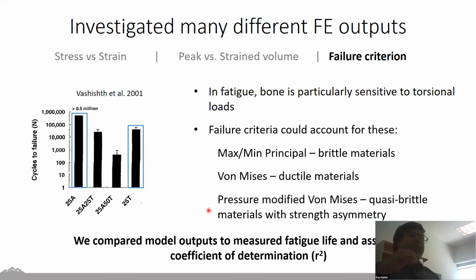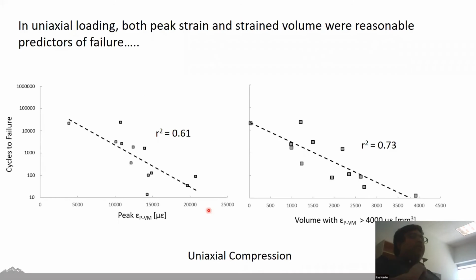I think the way I'll do it is I'll start by showing in detail a few of our regression relationships, the ones that really highlight some of the key findings from this study. But then to speed things along, I'll just show you the rest of our data in tabular form. So jumping right in, one of the very interesting things we found was that in the uniaxial loading condition, both peak strain and strain volume were reasonable predictors of failure. And that's what I'm showing here.